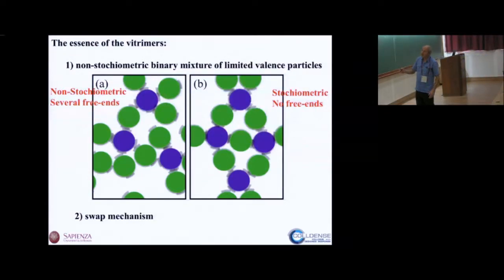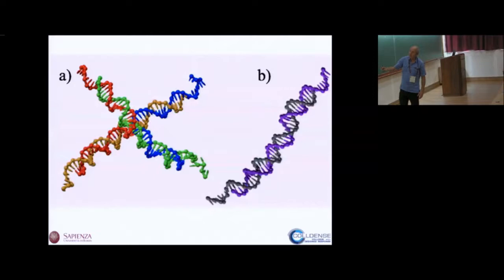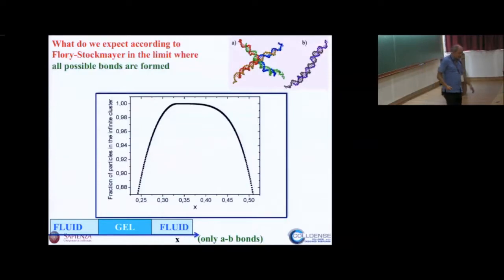You work with a binary mixture. In particular, we use nanostars of valence 4 and nanostars of valence 2. And of course, if you work at stoichiometric ratio, then the system is fully bonded at low temperature, and there are no free ends in the system. But if you work off stoichiometric, so you put a majority of particles with valence 2, then you get a reasonable number of free ends in the system. And we can use those free ends to activate a swap mechanism. That's what we want to do. So those are our particles, particle with valence 4 and particle with valence 2. We mix them at non-stoichiometric concentration, and in principle we should be able to design a swap mechanism and see these dynamics.